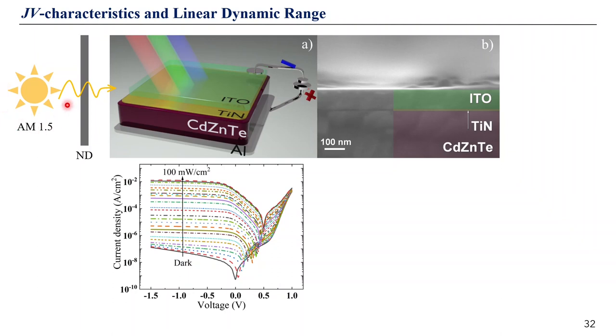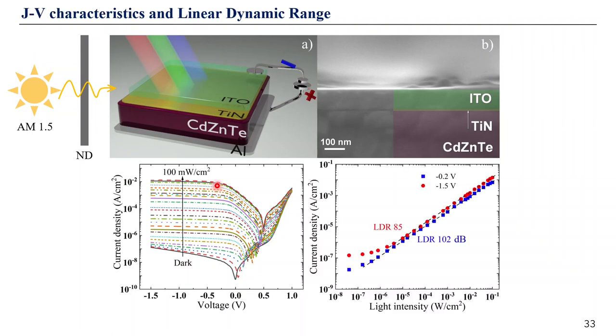So we used a conventional AM1.5 solar simulator with a set of neutral density filters, and measured IV characteristics at many different light intensities. So the key here is to check how photocurrent density scales up with light intensity. And we want to see linear dependence of photocurrent versus light intensity in as broad a light intensity range as possible. So the parameter which defines this is linear dynamic range. And for low reverse bias, we reach quite high linear dynamic range, above 100 decibel, which is exceeding analogs based on compound semiconductors.